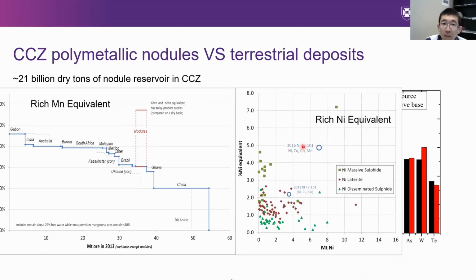And then another thing that we compare is the nickel grade between the nodules and the nickel ores. So as we can see, the nickel grade in the nodules is comparable with the nickel laterite. And for the sulfide, normally the land-based nickel sulfide is in depletion. However, we can find comparable nickel grade in the nodules, but in a very high amount of deposit.